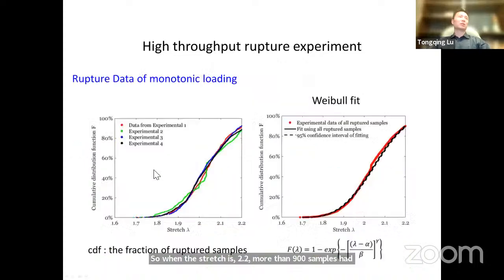Here are the experimental results of the monotonic rupture experiment. The 4 lines mean we did 4 rounds of experiment. Each round has 1,000 data points. The vertical axis is the cumulative distribution function, CDF for short. CDF just means the fraction of ruptured samples.